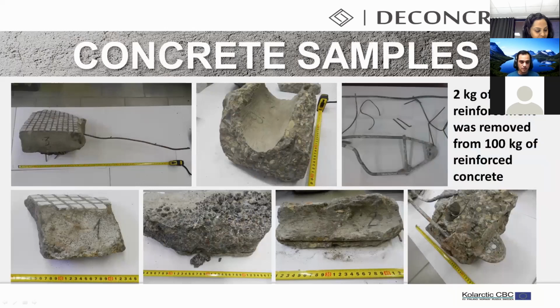We took these concrete samples and manually removed the reinforcement; it was about 2 kilograms of reinforcement from 100 kilograms of reinforced concrete. As you can see, there is a sample of lightweight concrete with silica and ceramic mosaic, and heavy concrete. There is also mineral insulating material, mostly consisting of shungizit, a material mainly of alumina and silica. It's a very porous and light material.